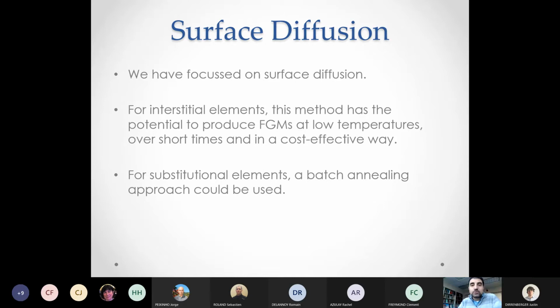The other approach we tried more recently was to introduce a gradient of the substitutional elements. And of course, that takes a much longer time because of the slow diffusion of the substitutional elements, but it can be done in the case of batch annealing processes, which give up to 24 hours or even 48 hours of exposure at high temperature.